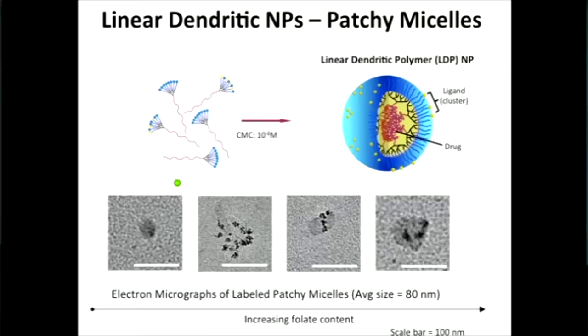This work was done before our cryogenic TEM microscope arrived on campus. And for those of you who do any kind of electron microscopy imaging, you know that typically we're in the dry state. As we move along, you'll see systems in which we are looking at the system in the hydrated state. But in this early work, what we did was cast the micelles onto surfaces in the dry state and label them with a dye which labels, using an atomic label, the clusters. And we can see that we can make micelles with many small clusters or with a few large clusters and everything in between.